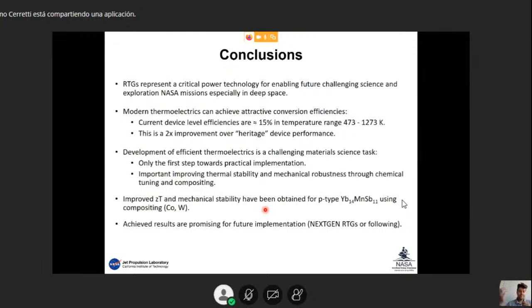So to conclude, I tried to show you and convince you how important RTGs and thermoelectric technology are for enabling future and hopefully more challenging NASA exploration missions, especially in deep space. Modern thermoelectric materials can achieve attractive conversion efficiencies. At this moment, with the materials we are developing, the device level efficiencies are about 15%, and it's a huge increase compared to what we had before with the silicon germanium couples, where the MMRTG arrived at a top performance of about 7.58%, and the silicon germanium was about 6 to 6.5%.